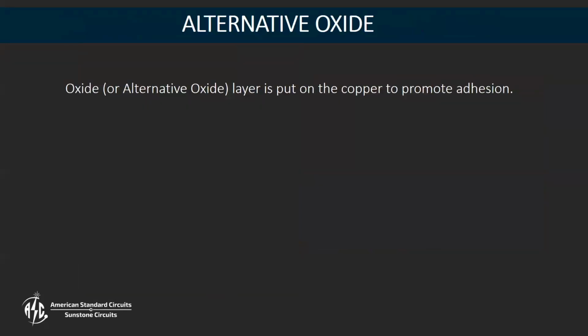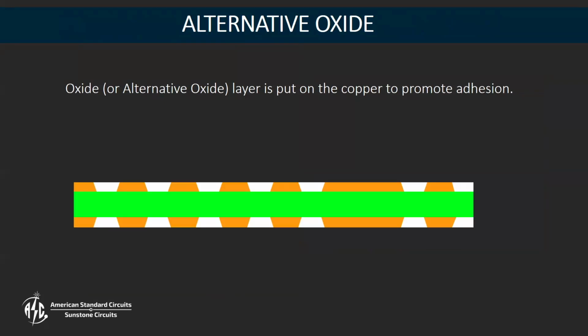In order to get good adhesion of these copper layers during lamination, we have to run it through a chemical process, an oxide or alternative oxide process that roughens up the surface of that copper and makes it more prone to adhering to the epoxy during the lamination process. So this will be what our core looks like. We're going to go ahead and put this oxide coating on it, and you can see we've added a blue layer to the top of the copper, which is basically that adhesion promoter.